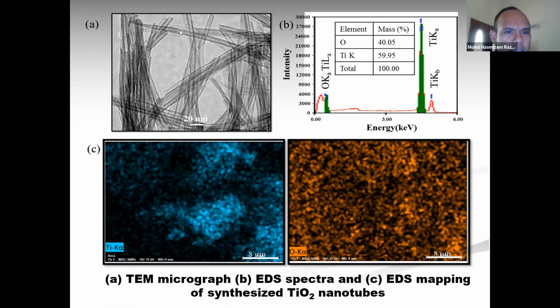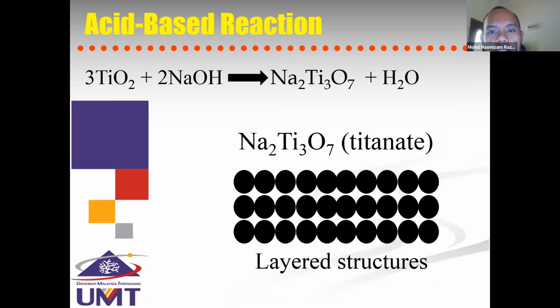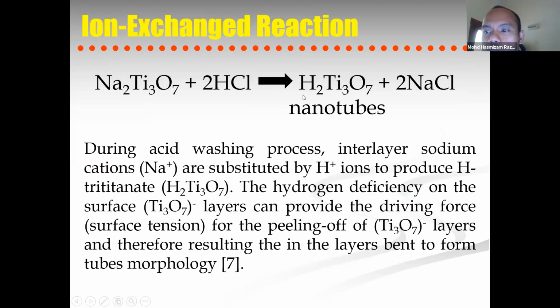Here we can calculate the diameter of the nanotubes. In the EDX analysis, we observe titanium around 60% and oxygen 40%. Then we come to the mechanism of how the commercial titanium dioxide is transformed into titanium dioxide nanotubes. This is the reaction: the commercial TiO2 reacts with sodium hydroxide during the hydrothermal reaction to produce sodium trititanate. Then by washing with hydrochloric acid, we observe the formation of hydrogen trititanate nanotubes.